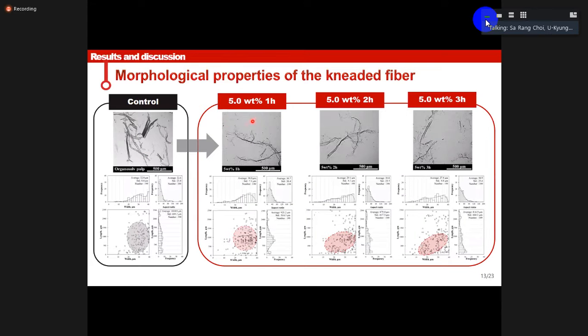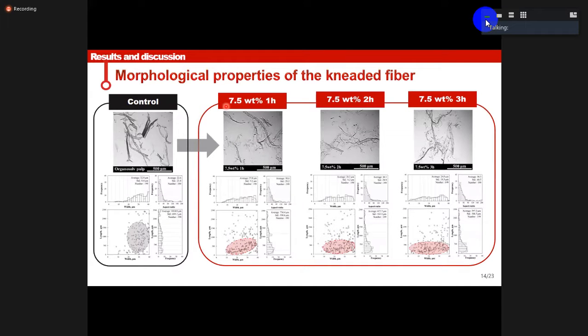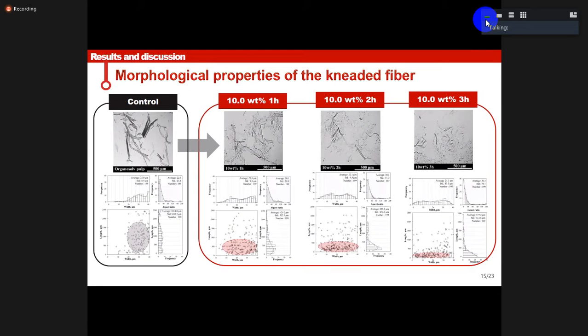When the pulp was kneaded at a concentration of 5%, the fibers were fibrillated and fiber length and fiber width were reduced. Also, the micronization was clearer when kneaded for 3 hours. This slide shows the pulp kneaded at 7.5% solid. They also micronized, and the fiber size decreased more with longer time. And at the concentration of 10%, micronization was remarkable, and the fiber size was most reduced when kneaded for 3 hours.